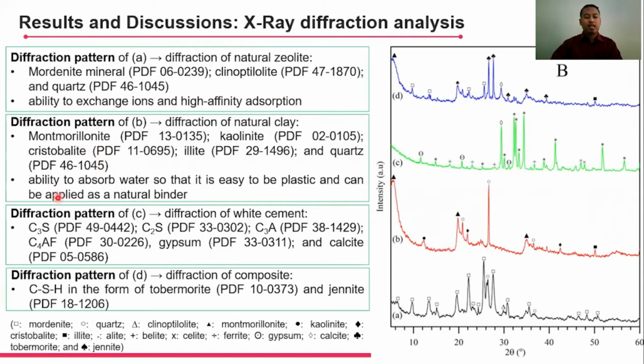The montmorillonite gives the ability to absorb water, so it is easy to be plastic and can be applied as a natural binder. The diffraction pattern of C is the diffraction pattern of white cement. From this diffraction, we get the presence of tricalcium silicate, dicalcium silicate, tricalcium aluminate, and the last is tetracalcium aluminoferrite, gypsum, and calcite. And the diffraction pattern of D refers to the diffraction of the prepared composite, and we get information about calcium silicate hydrate in the form of tobermorite and jennite mineral.